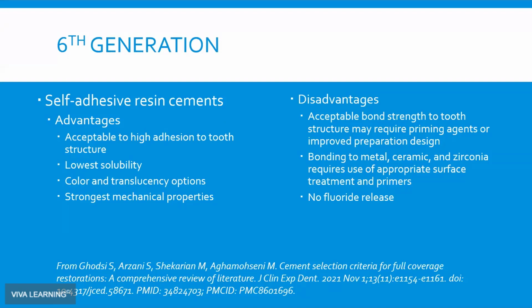So with the self-adhesive resin cements, I put them in there, maybe it should be a 5B generation, but either way, they're excellent in their resin form if you prime stuff. And when it says self-adhesive, that meant self-adhesive to tooth structure. It did not mean self-adhesive to other materials without priming. So even if you had in those days composite inlays, onlays, and even composite bridges were kind of popular, they really still required silination and priming preparation. So really, when we say self-adhesive resin cements, I put them in their own kind of category because they did require priming of all substrates.